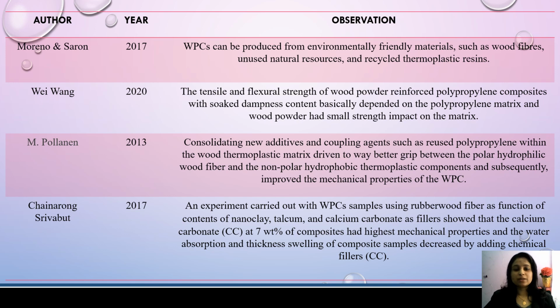Next, M. Pollanen in 2013 mentioned that consolidating new additives and coupling agents such as reused polypropylene within the wood thermoplastic matrix led to better adhesion between the polar hydrophilic wood fiber and the non-polar hydrophobic thermoplastic components, and subsequently improved the mechanical properties of WPC.